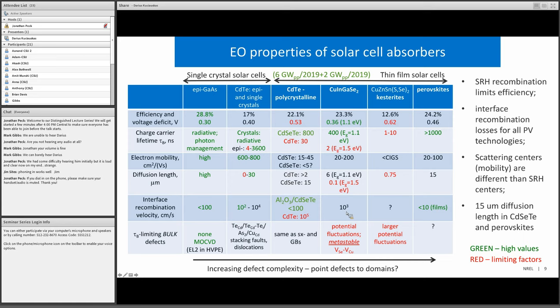And when we know the specific defects that limit carrier lifetimes, then good feedback is possible to researchers who grow the materials. For example, if tellurium on cadmium site is the recombination center, then increasing the cadmium density by using cadmium overpressure or higher temperature growth would reduce this kind of defect and would increase the carrier lifetime.